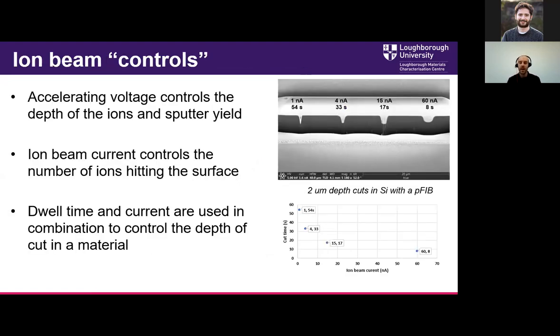So what controls do we have over the ion beam? It's actually quite similar to an electron beam in that our accelerating voltage essentially controls the depth that the ions penetrate into the surface, and the current controls the number of ions hitting the surface for a given time. And so this allows us to change how quickly we cut something and also how accurately.